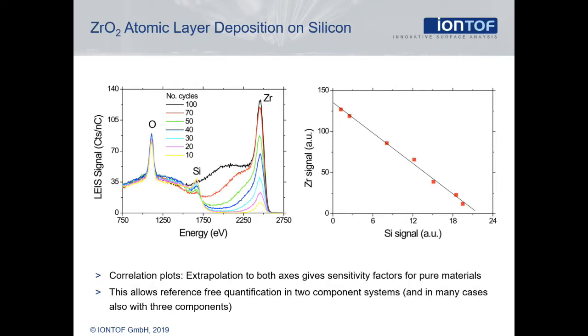This anticorrelation can be shown in many elemental combinations and is universal except for some known elements. Here is an example of zirconium oxide growth on silicon: the more zirconium is detected, the less silicon signal there is. Besides demonstrating the absence of matrix effects, these plots also have a practical use for quantification. When the straight line can be fit to a few data points, the intersection with the two axes shows the intensity for the pure material, yielding the sensitivity factor for each element. To draw the line, only a few samples with different ratios of the two elements are required — in particular, the pure material is not needed. With sufficient samples, this way of quantification can also be applied to three or more elements in the sample.